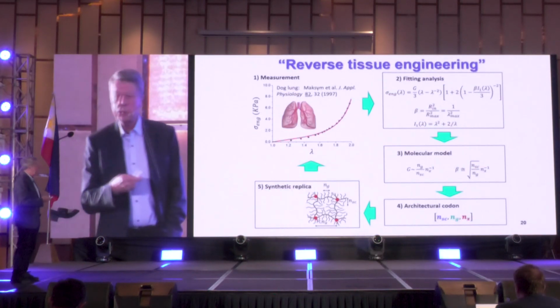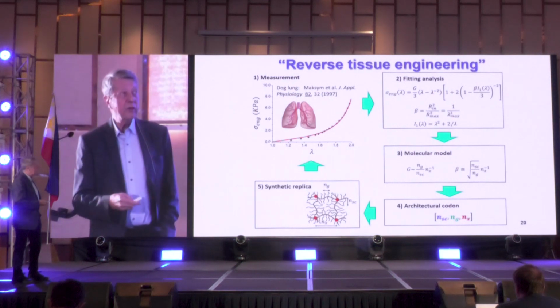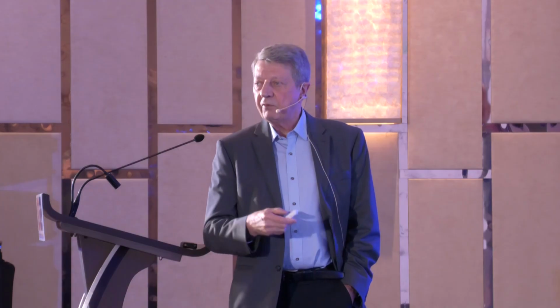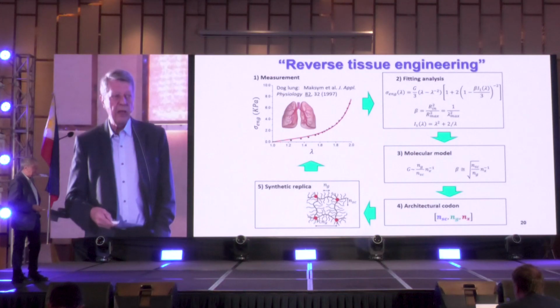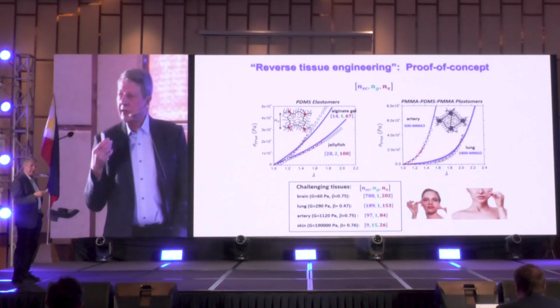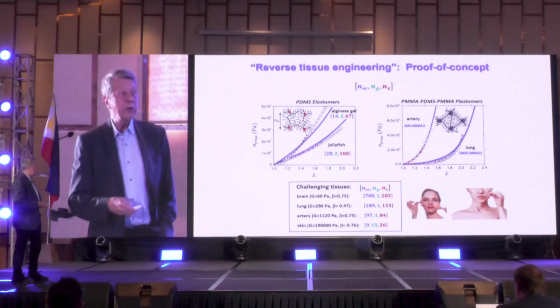For example, if you take a dog lung, in that case, you will see this strain hardening, and then through some artificial intelligence and machine learning, we can fit this analysis and convert them into these 3 parameters: length of a side chain, grafting density, and cross-linking density. So you could see here, if we design it in a proper way, we can mimic the alginate gel, we can mimic jellyfish, we can mimic artery or even lung. And you can go even to a softness of brain.